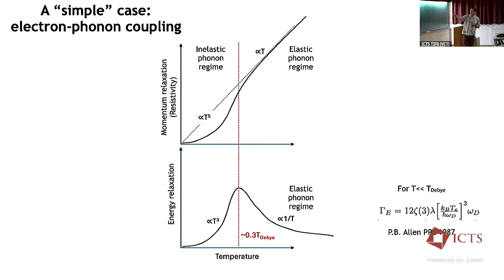And then there's a peak at the same temperature where we go to linear in T. And then it's actually a decrease in the elastic phonon regime. And that's just perhaps for the obvious reason that when you go to high enough temperatures, the electrons, again, have a lot of energy. They have a lot more energy than the phonons do because the phonons are limited in energy to the Debye temperature. And the phonons are very inefficient to take away energy out of the electronic system.